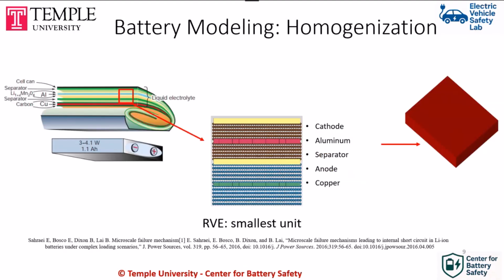But when we go to the jelly roll, which is the main energy storage part, it's not only one material. We have at least 4 main components, and the main components, we have aluminum foil, we have copper foil, and on top of that we have active coatings, anode and cathode, and then we have a polymeric separator separating these 2 from each other, and these layers are just like on each other without usually any gluing to each other. So depending on what type of loading we have, the behavior can be very different. Now we want to combine all of these layers into one material, which is a homogenized material that will represent the behavior of all of these layers.